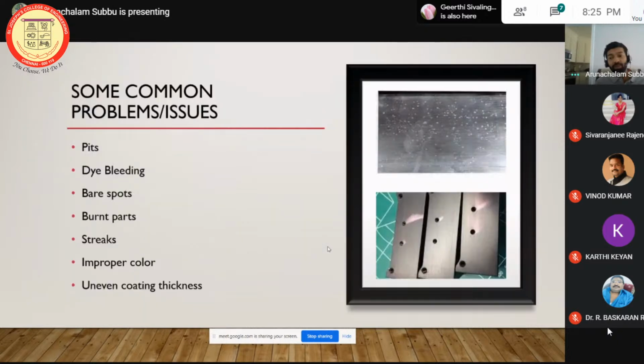Yeah, what are the common issues that you see in an anodized coating? We could see a lot of pits on certain parts when you use rinse tanks with a lot of chlorides or something like that. You should make sure that the chloride content is within limits, so that you don't get pits. And also the alloys like 2000 and 7000 series, you get a lot of pits because they have zinc in them, and that doesn't go well with the tank solution. So in that case you will get pits.